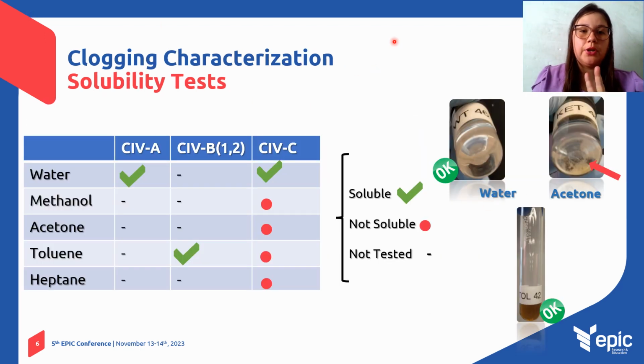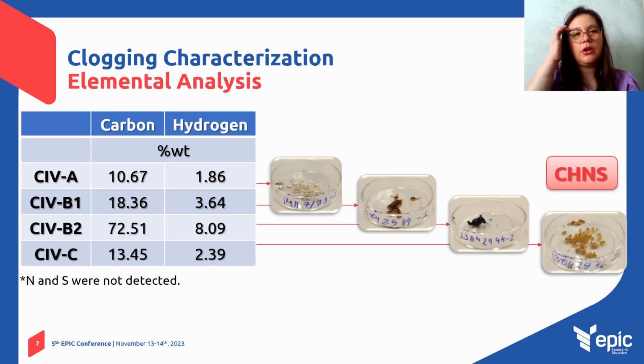Solubility tests showed the 2 chemical natures of the clogging materials, one inorganic and the other organic, with the samples from chemical injection valves A and C being soluble in water, and the samples from chemical injection valve B being soluble in toluene. These results are significant as they give us an idea of how the clogging material can be removed or cleaned from the chemical injection valves. Thus, the elemental analysis of the clogging materials also confirmed that there are 2 natures of the clogging materials via carbon, hydrogen, nitrogen, sulfur elemental analysis, where nitrogen and sulfur were not detected in the clogging samples.